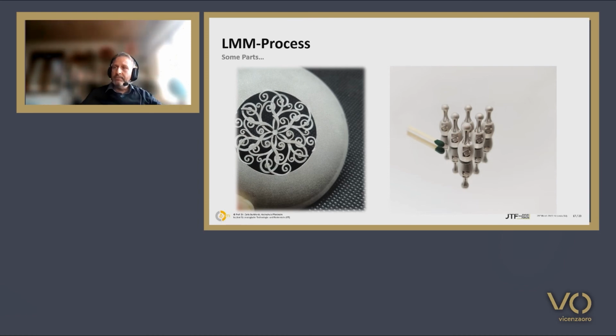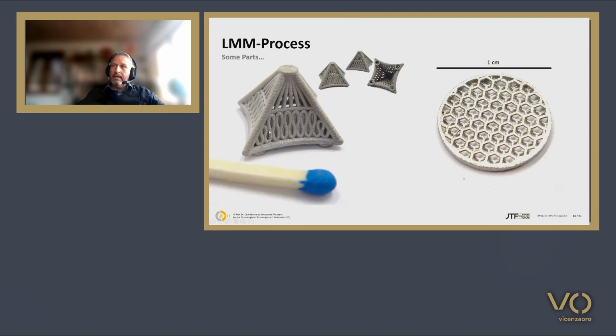As I said, I'm showing pictures here that have not been treated afterwards. On the right side, a little gimmick here for a trade exhibition. These are some structures just to show what is possible with the process. Here, printed parts, sinter parts on the right side. For scale, you always see either the matchstick or here, this is 1 centimeter. So you see a very, very detailed process, which gives you fine structures. And yeah, the disappointing thing is that the pictures look much worse than the real parts, because the resolution of the cameras is better than your eye.